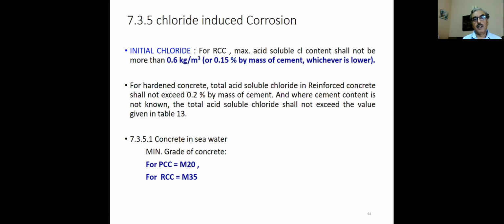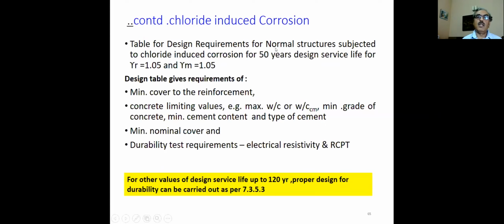Minimum grade of concrete for PCC is M20, for RCC M35, where chloride ingress is there. A table is given again here for 50 year service life, which gives minimum cover requirements, limiting values, and durability test requirements, similar to the carbonation process.